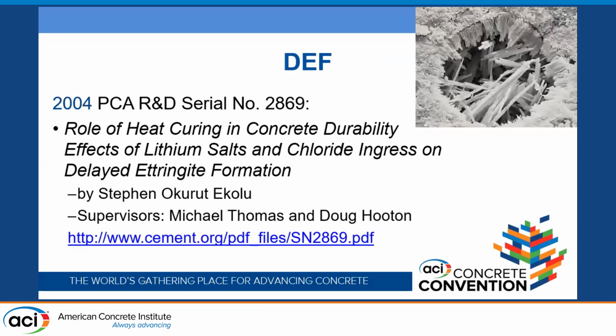Another program that he worked on was the role of heat curing in concrete durability due to the effect of lithium salts and chloride ingress on the DEF. So this was one of his students' work, Stephen Ekolu. This investigation was conducted in 2 phases on heat curing up to 95 degrees Celsius, and it was found that lithium could suppress and control DEF. It also showed that externally applied chlorides have a pessimum effect on DEF, and this deviated from a commonly held view that chlorides can help mitigate sulfate attack in marine concrete, as an example. So there was a mechanism describing the pessimum effect in this report that was useful to us as DEF came about in the early 2000s.